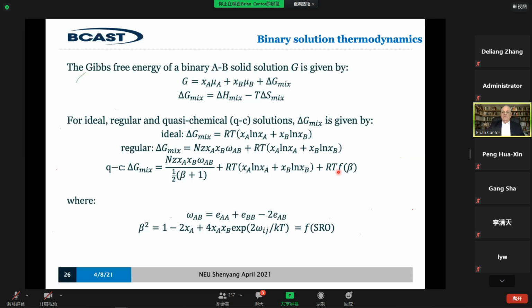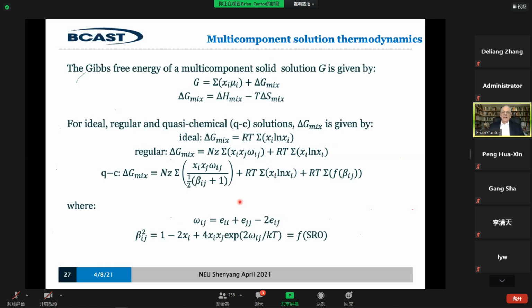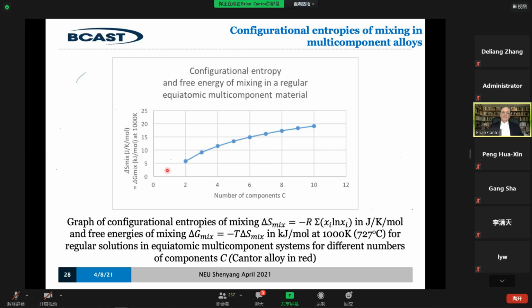If we go to multi-component solutions, it's not very different. For the free energy, we have to do a summation now over all the different components. So these become sums, but otherwise the structure is pretty much the same. There's an enthalpy of mixing and an entropy of mixing. The entropy of mixing is the random one here, the ideal one or the regular one. There's an enthalpy of mixing, an entropy of mixing, and an excess entropy. But we're interested in this configuration entropy because we've got a large number of components. And how does it compare to the enthalpy? So this is the entropy. It goes up as you increase the number of components.